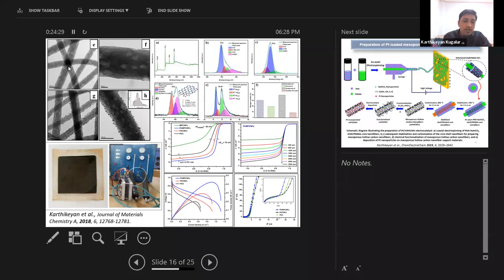This is the material which we have developed using the electrospinning technique. We have created a porous structure, porous carbon nanofibers. Basically, we have used polyacrylonitrile polymer solution for producing the nanofibers using the electrospinning technique. Then we have treated this nanofiber using a thermal annealing process, and we converted this polymeric nanofiber into porous carbon nanofibers. We have mixed in sodium bicarbonate nanoparticles. When we treat at the higher temperature, the sodium bicarbonate nanoparticles will come out from the nanofiber, and that will create tiny pores inside the nanofibers.